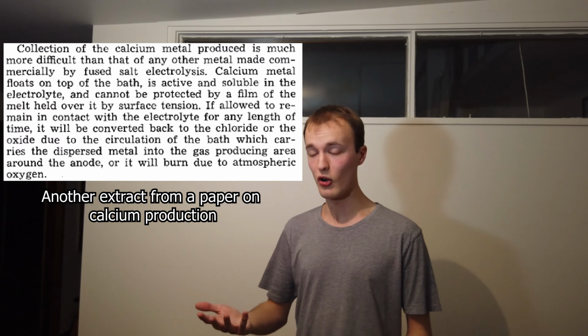So molten calcium chloride, something like that, has a very significant solubility for calcium metal. And as a result, if you try generating calcium metal by the electrolysis of molten calcium chloride, the calcium metal will pretty much dissolve into the melt just as fast as you generate it. Nonetheless, we're going to have a go at it.